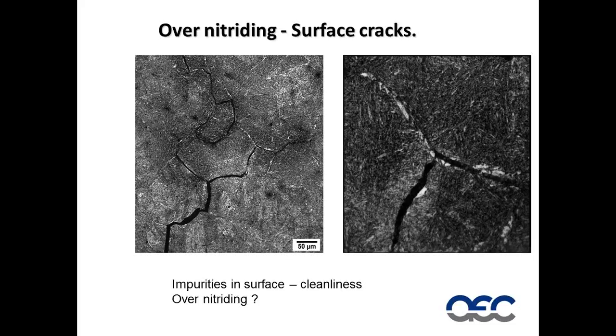Quite often people handling dies when they're putting them in the nitriding oven, if they don't think about it, use the gloves that they normally use for handling dies. And these are covered in various greases and lubricants from the extrusion plant. So these are transferred onto the surface of the dies when they're put into the nitriding oven. The presence of these impurities or lubricants is a bad thing and leads to this form of surface cracking and also can lead to soft patches on the die.